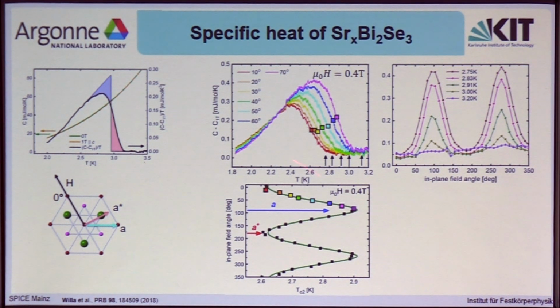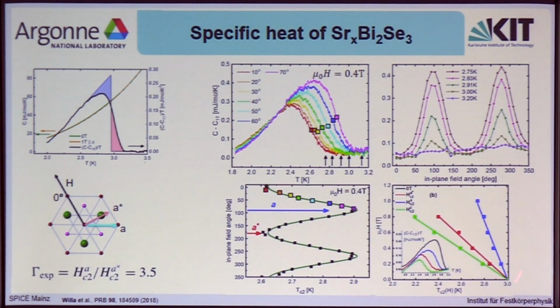Now, of course, once you have these maximum and minimum axes, you can extract the phase boundary for the system, and you can plot here for the a-star axis and here for the a-axis the upper critical fields, and also here you clearly see this rather large anisotropy of something between 3 and 4.